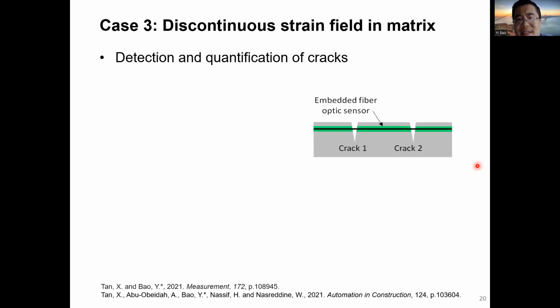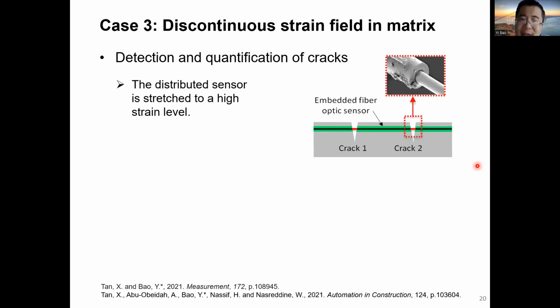But then we realized that in many cases, the strain field condition is not continuous. It could be discontinuous. For example, if you have a crack, the crack will cause discontinuous strain field conditions. At first, we were concerned that the fiber optic sensor will be damaged because of the crack, right? Because the glass fiber is very fragile. But we did the testing and we found that the crack didn't rupture the fiber optic cable because debonding could happen between the glass fiber and the polymer coating.